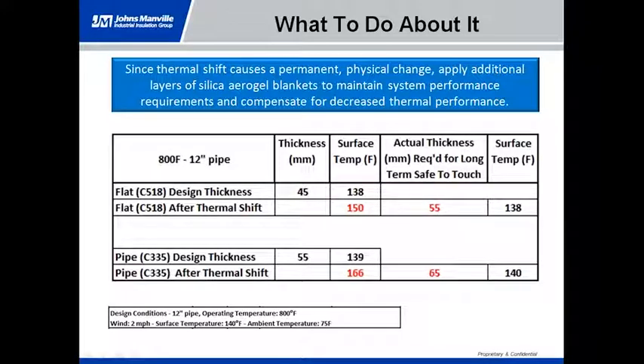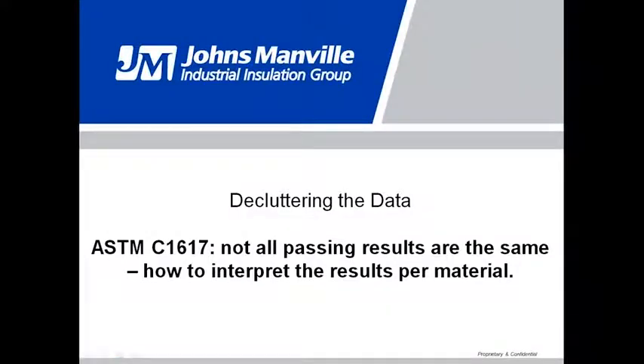Of course, we know that our pipe data is not going to perform as well as our flat data. So our initial thickness, we start with a 55 millimeter thickness for 140 degrees. But again, if we use our thermal shifted data, surface temperature is now 166 degrees. So again, we have to add additional thickness, or 10 millimeters, to make a 65 millimeter thickness to get our surface temperature down to 140 degrees. So long story short, those materials can be used, but there are some things that you need to do. If you are going to use that material, you're going to have to add at least one layer to make sure that you're bringing your temperatures and your heat losses down to what they were prior to that compromised value.